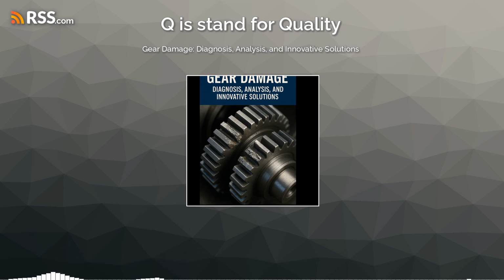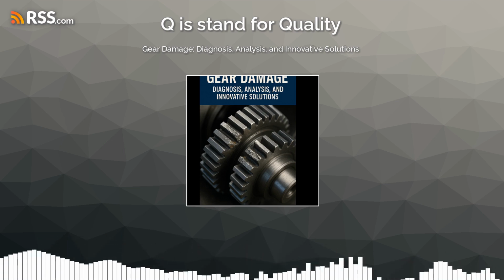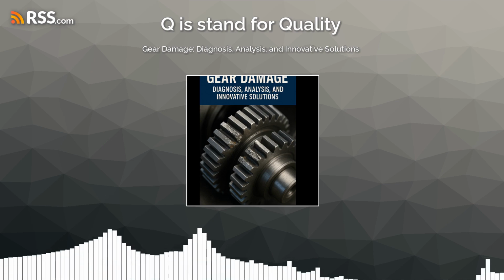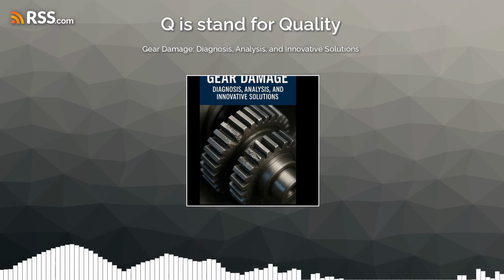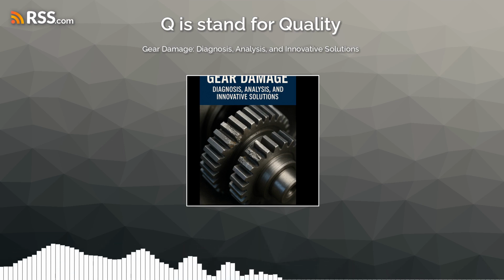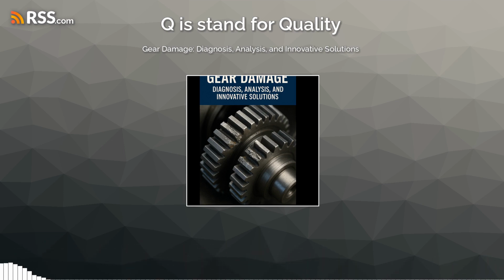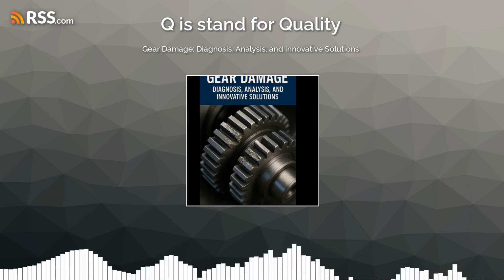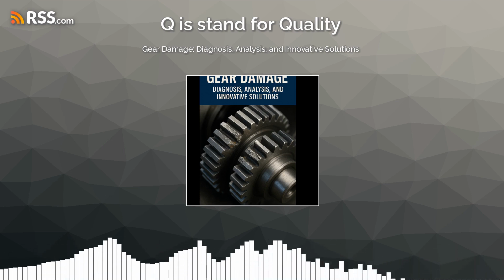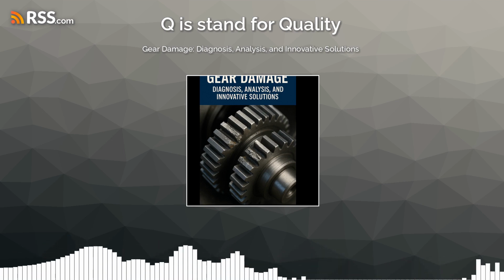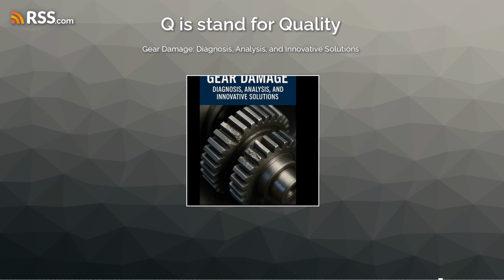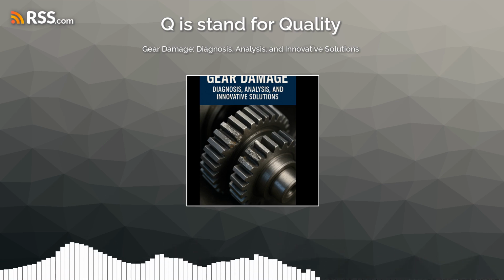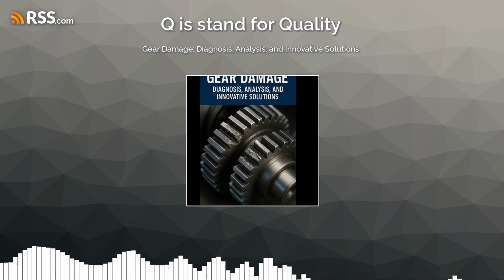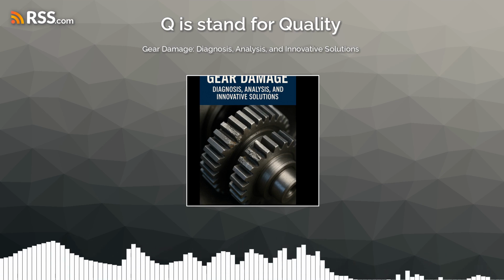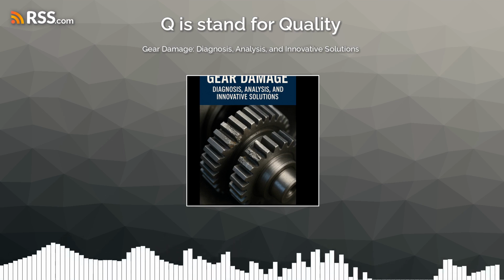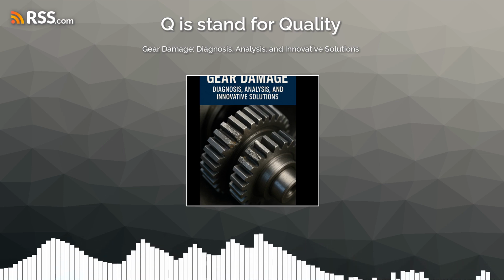Okay. Over time, these cyclic stresses start microscopic cracks, which slowly grow. They weaken the material bit by bit until the remaining part can't even handle the normal operating load anymore, and boom, complete fracture. Interestingly, the source notes that often a crack started by an impact, even a small one, can slowly turn into a fatigue crack. And sometimes you see signs of fretting corrosion near where it started. Fretting corrosion, what's that? It's a specific type of wear and corrosion that happens at the contact points between materials under very slight relative motion, like tiny vibrations. It can produce fine debris and actually help initiate cracks. It's a subtle clue in the forensic analysis.